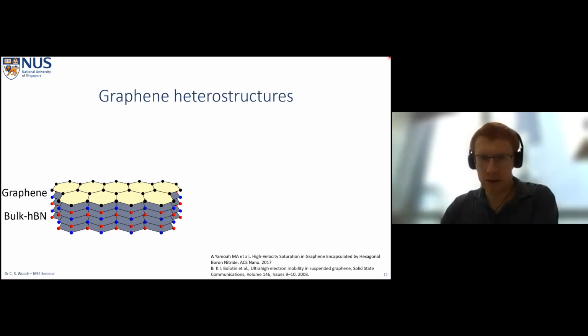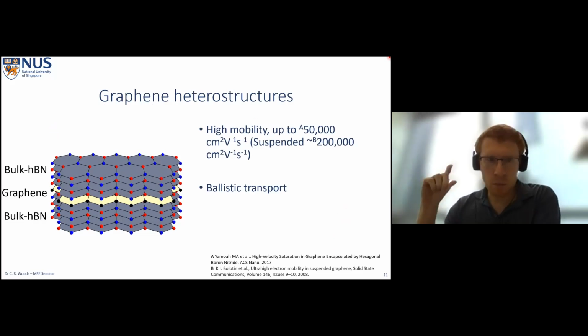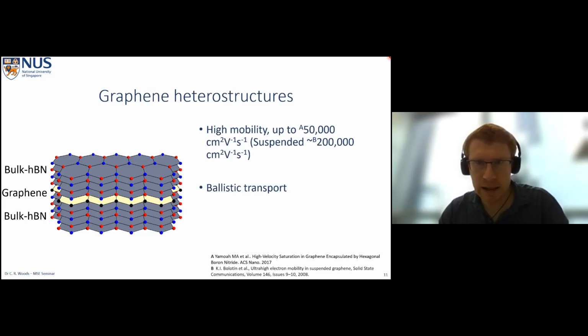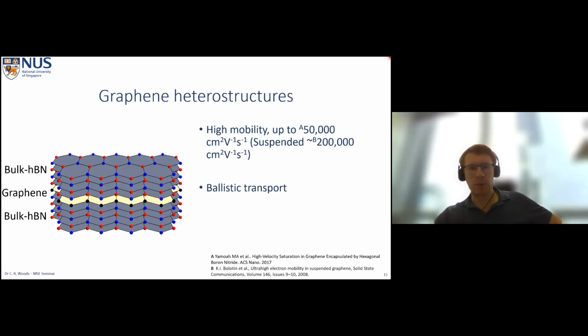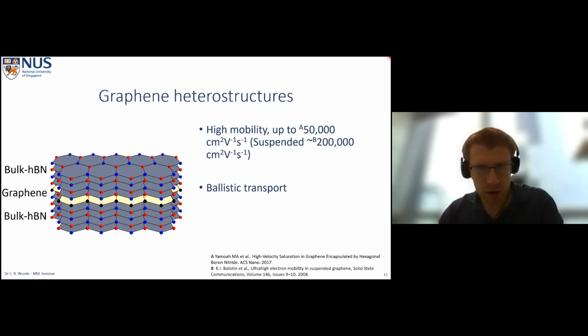So the best known example of this is we just then take boron nitride as a substrate, take boron nitride as an encapsulation layer for graphene, and we can get extremely high mobility electronics in the graphene layer in the middle. And this is probably one of the simplest heterostructures being produced, but it serves the purpose of explaining that boron nitride is being used as this very nice dielectric substrate for all of our van der Waals heterostructures. And all of the crystals that I showed you before, we're using hexagonal boron nitride for all of them to try and get the best out of their properties.